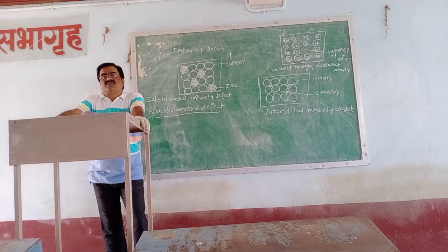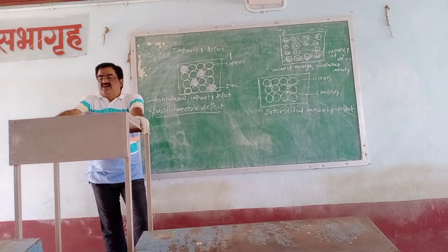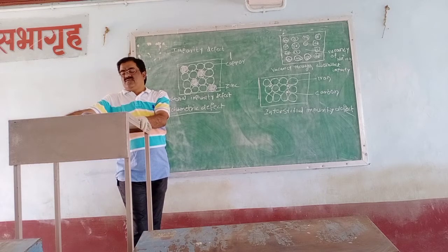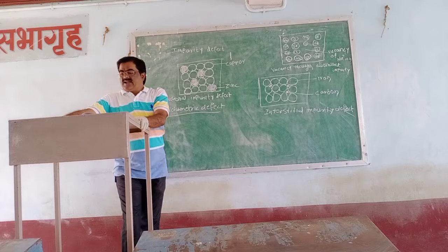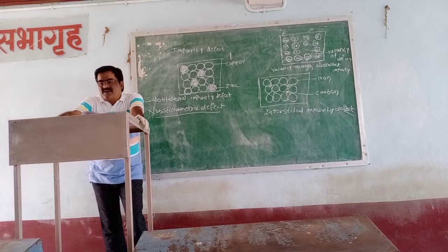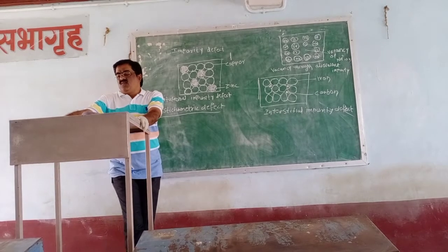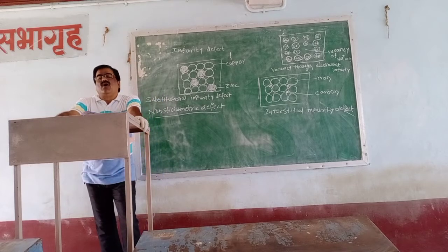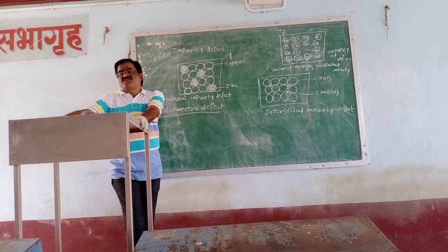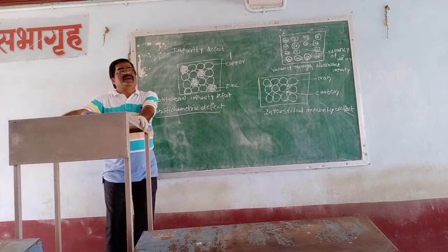During its crystallization, the added Sr ions occupy some of the regular sites of the sodium, which is the host ion. And in order to maintain electrical neutrality, every Sr ion removes two sodium ions. One of the vacant lattice sites created by the removal of two sodium ions is occupied by one Sr ion, and the other site of the sodium ion remains vacant, as in this figure.